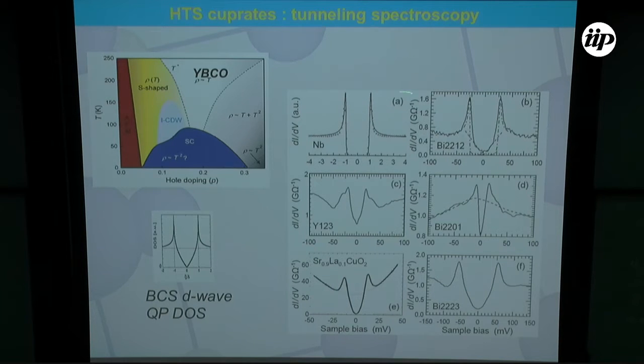You have here a niobium superconductor, where the tunneling spectrum is really a textbook S-wave superconductor, BCS. But you see here Bismuth 2212, 2201, YBCO or LSCO. The tunneling spectra are really different from what is expected for a pure D-wave superconductor.